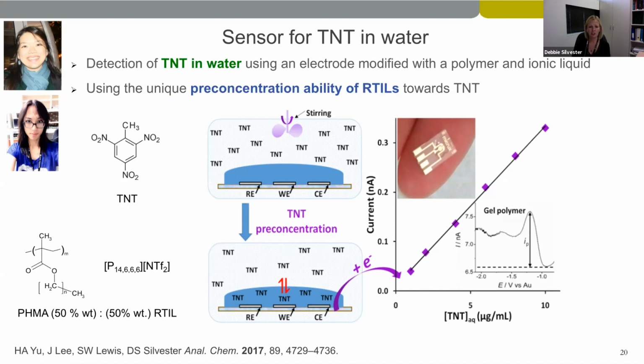It's been shown by other groups that ionic liquids have a very unique ability to pre-concentrate explosives like TNT. So there's a very high solubility. And because of this, we now can have TNT in the gel polymer phase, and then we can apply a potential and observe a current response to detect the presence of TNT.